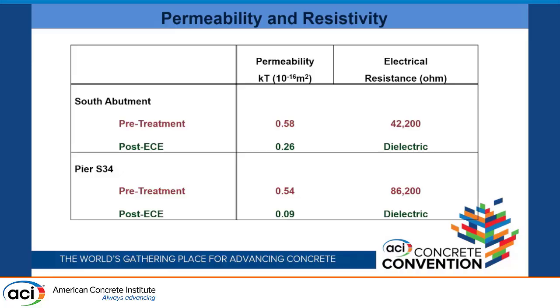And so this effect also plays in with some of the bond issues and whatever. So when you draw all the sodium towards the steel, you create those salts, which are very soluble, unlike calcium salts. So what you see happening when you use lime, for example, is that it plugs up the pores of the concrete, particularly at the surface, and it makes the surface permeability go down a lot. And you see the same thing happen for electrical resistance reasons as well.